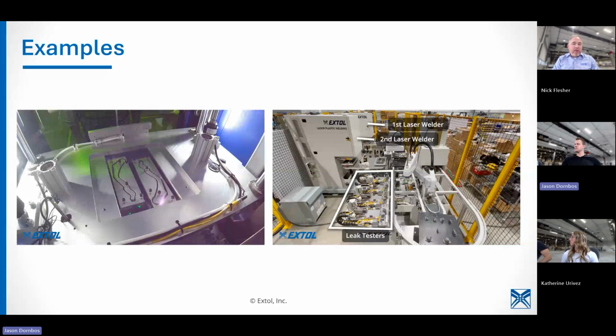Here's what I would say. Typically, most laser welding companies don't apply the kind of force that we apply. I've seen us be successful in applications where others weren't because we're using hydraulic pressure, like 6,000 pounds of force. Now that was a very wide weld rib, but we will fine tune that pressure. That's really, really critical.